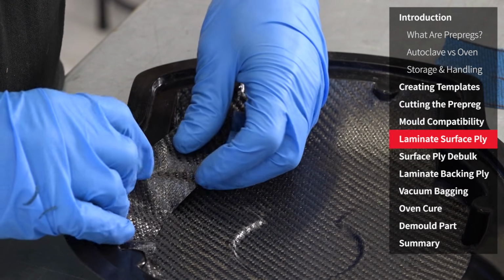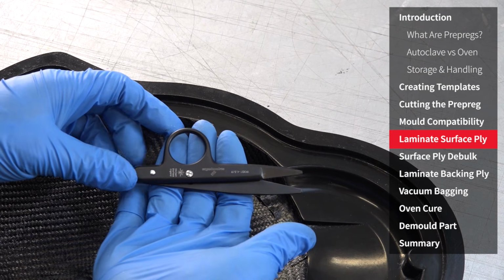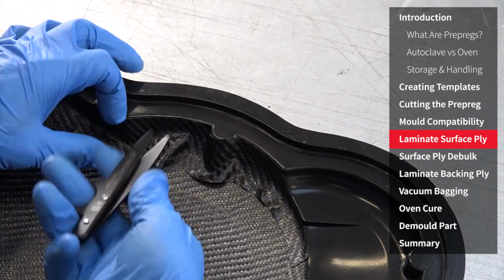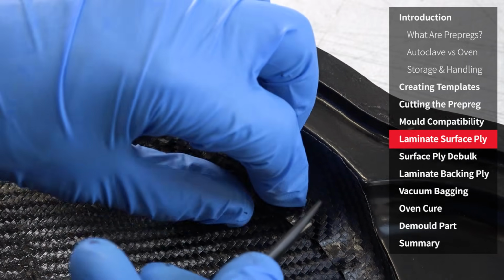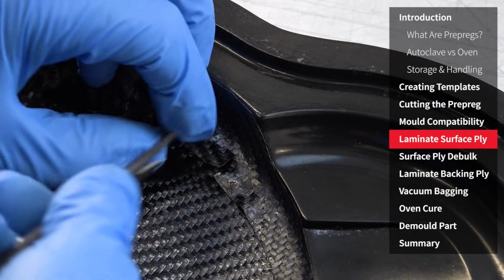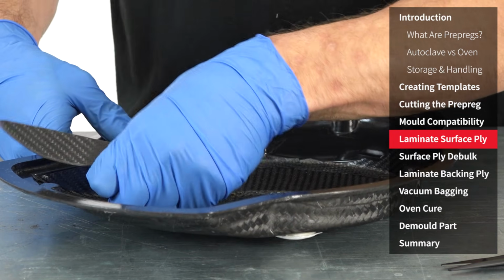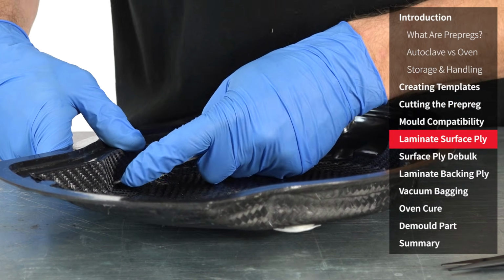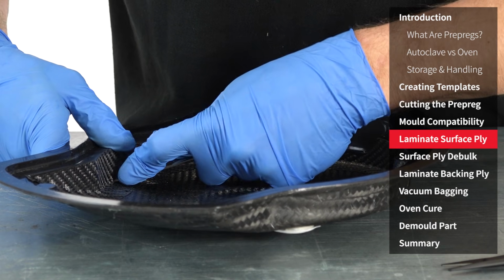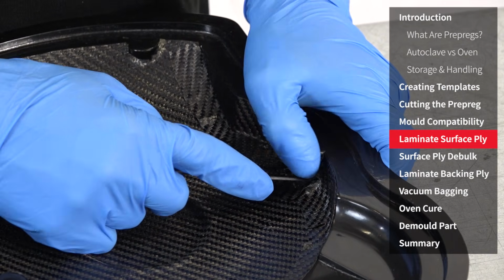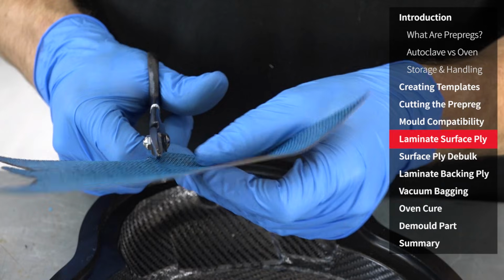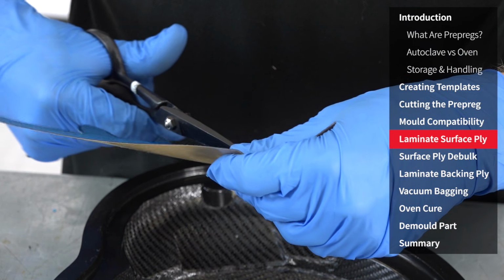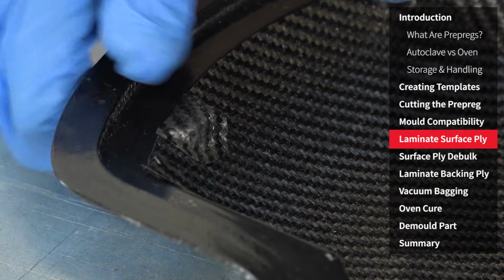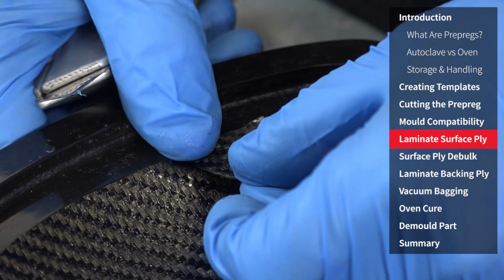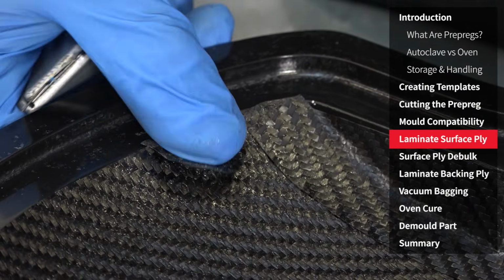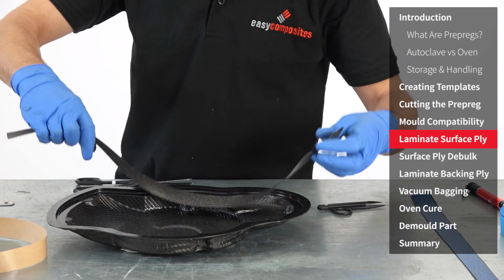To maintain strength, the second piece of prepreg has been made to have an overlap with the first. Due to the geometry in this area of the mould, it would be difficult to laminate without creases, so I'm using some composite snips to cut the material and allow it to lap. 9 times out of 10, laminating faults are due to not properly pressing the material into negative corners and features in a mould. Although, as I discussed earlier, placing joins in these areas will help reduce the risk of bridging, you still need to pay these features extra attention. You will notice that some of the smaller details on the moulding I didn't template for. In this case, it's easier to cut the pieces by eye as they are needed.